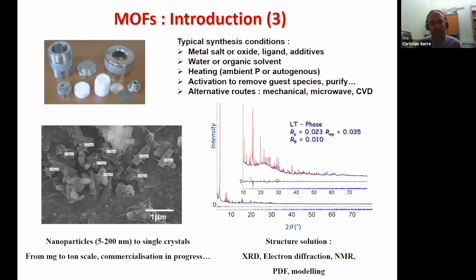There are many ways of making a MOF that are not hydro or solvothermal conditions. You can use solvent-free synthesis with thermomechanical synthesis, or you can combine with a different source of heating. Instead of electrical heating, you can use microwave or ultrasound. And more recently, some people developed even some sophisticated routes to produce MOF films, for instance, by chemical vapor deposition.